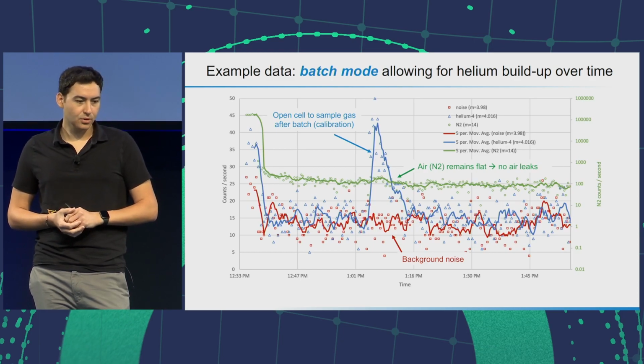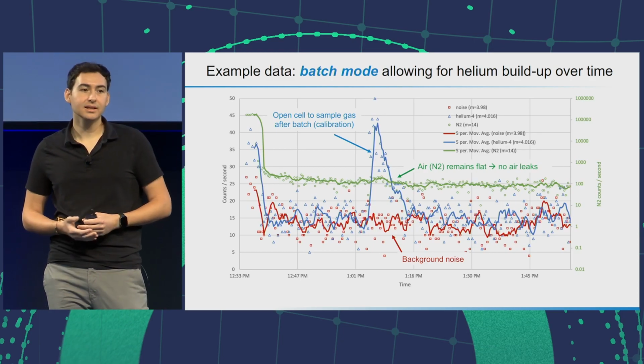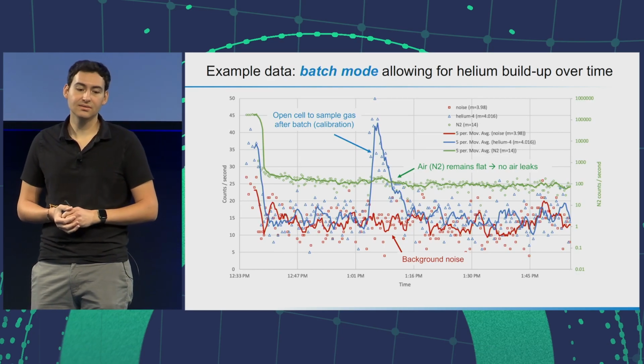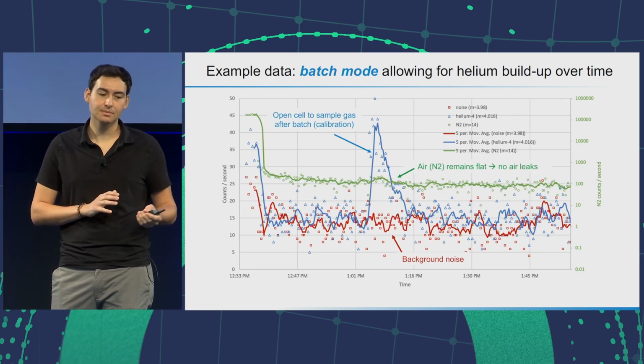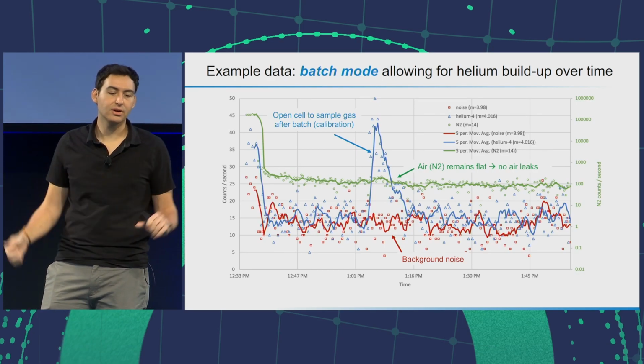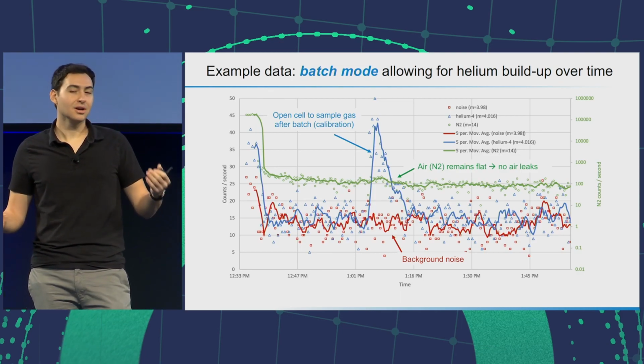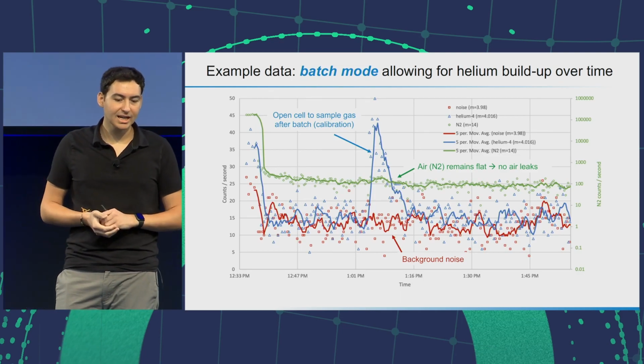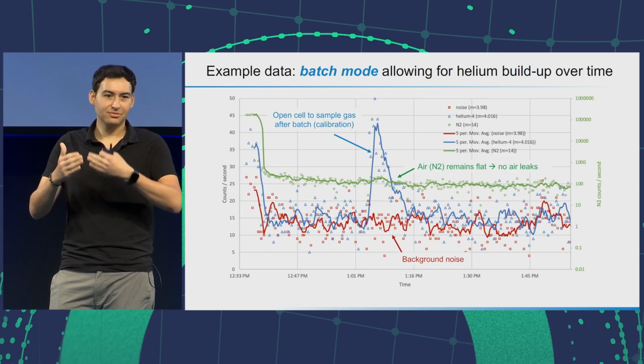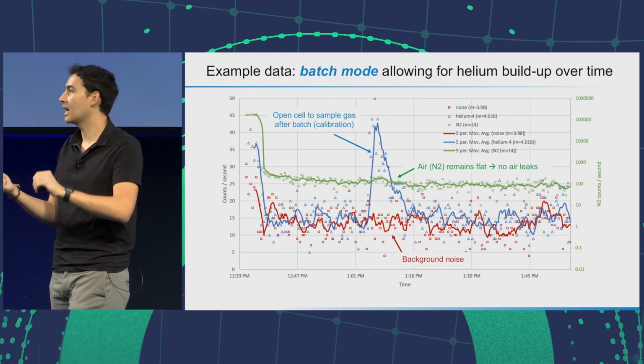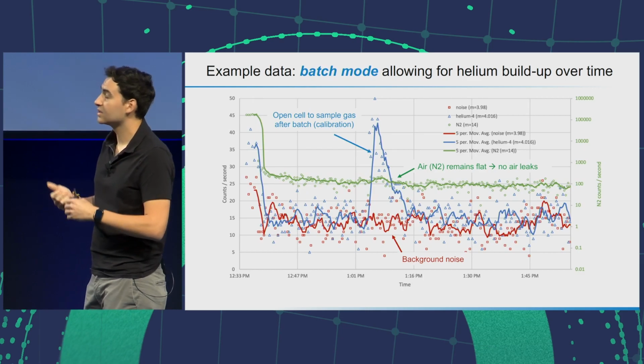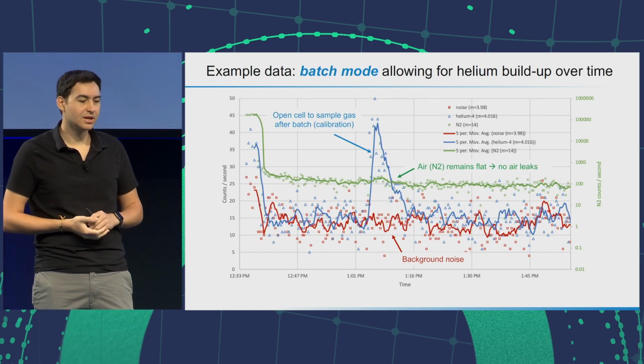If we really are focused on maximizing helium detection and increasing sensitivity, we could trade off that real-time piece, batch up our reactor, close off the valves, and let it sit for 1 hour, 1 day, 1 week, however long we like, and then, in the hopes of building up helium over that time, sample the reaction all at once and see if we see helium. And so this was another calibration test.